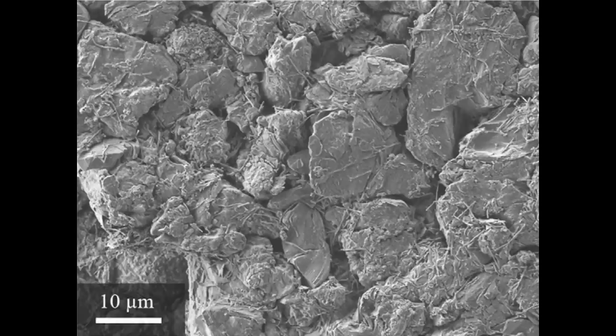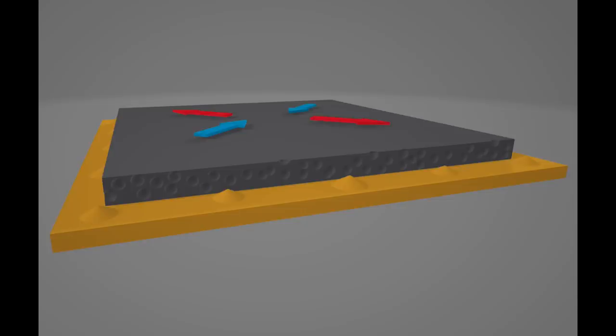However, too much porosity reduces energy density. With the silicon anode, porosity needs to be very high to allow for expansion and contraction. If there's not enough porosity to allow for expansion and contraction, the anode will separate from the foil backing. The porosity of a conventional lithium-ion battery anode is 30 to 40%. The porosity of the SiILion C-PAN anode would need to be 50 to 70% to allow for expansion and contraction.